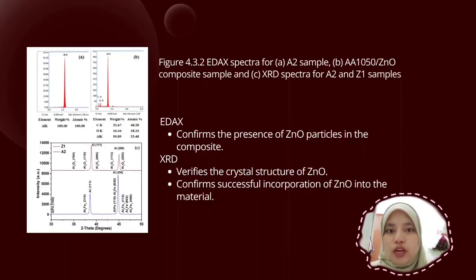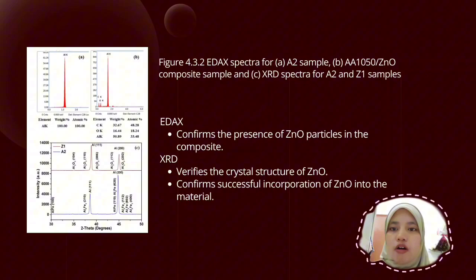So from the spectrum, we can observe the presence of zinc and oxygen peaks, confirming that zinc oxide is successfully incorporated into the composite material. The higher intensity peaks indicate a higher concentration of those elements. Therefore, the EDX result verifies the elemental composition of the material and confirms the successful addition of zinc oxide, which contributes to the improved corrosion resistance observed in previous tests.